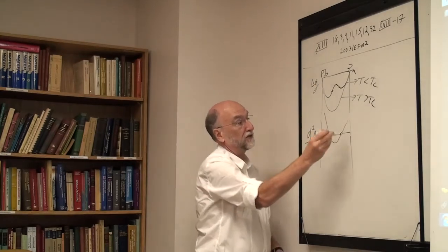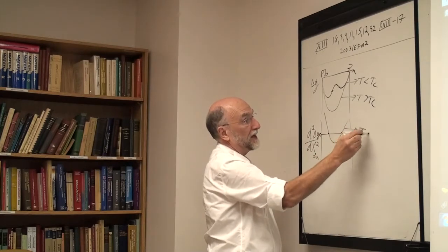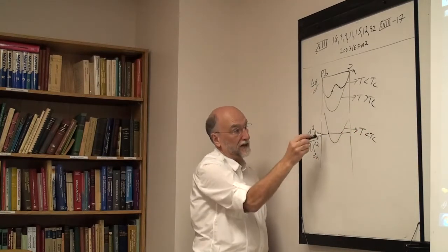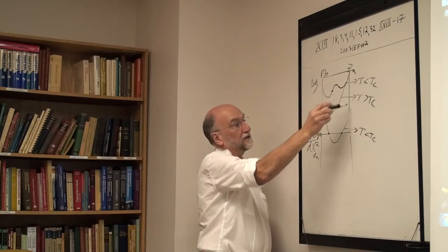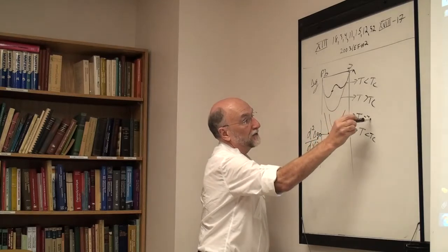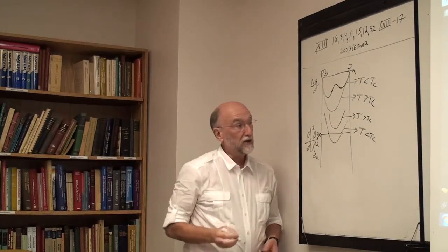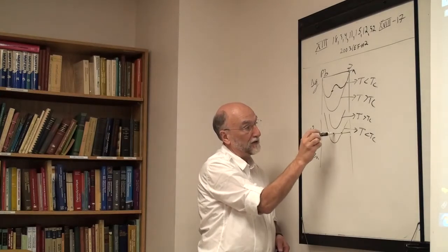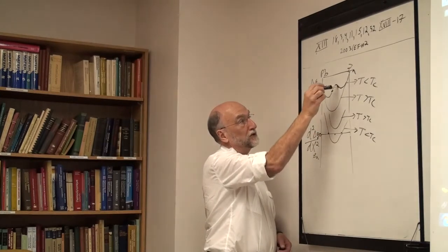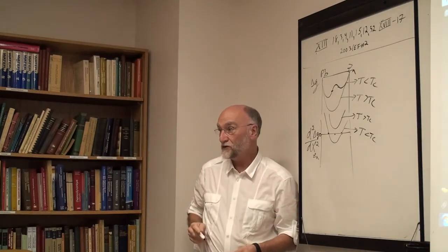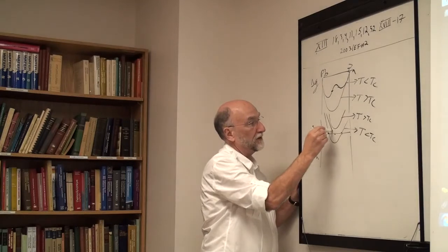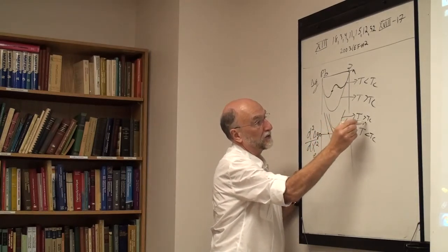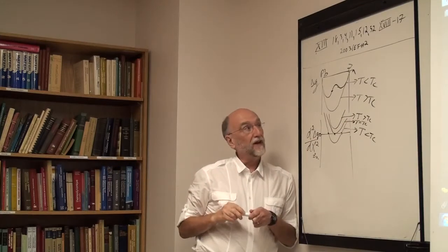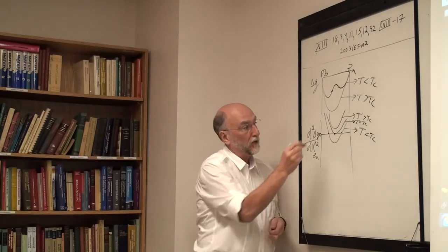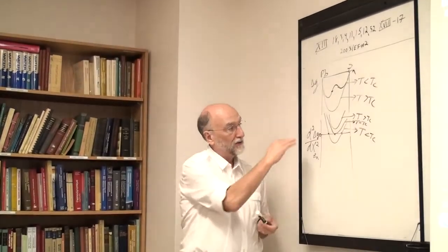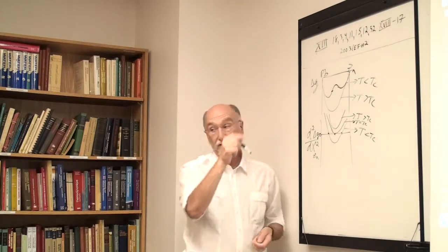Okay, so the second derivative, this is for T less than T critical, going through zero, going from positive to negative. If T is greater than T critical, then the second derivative is going to be positive everywhere. And obviously when T equals T critical, it's just the point at which the second derivative goes to zero at one point, or in other words, when these two inflection points become the same point. So clearly the critical temperature is the point at which the second derivative just goes to zero at one point, and that point will be the critical point.